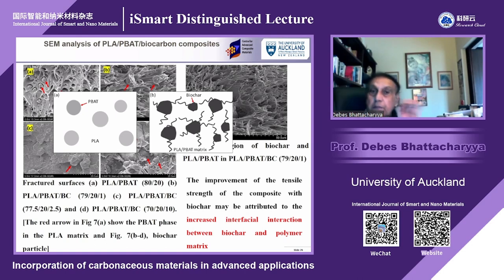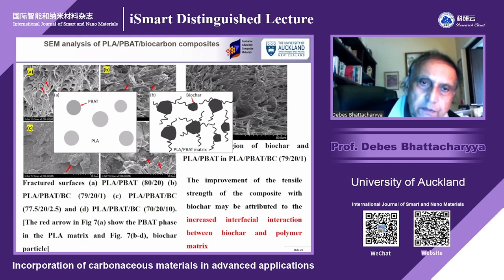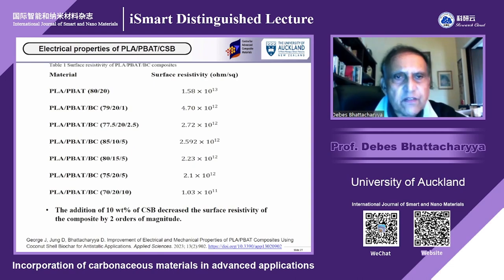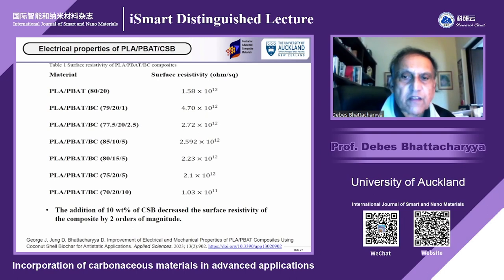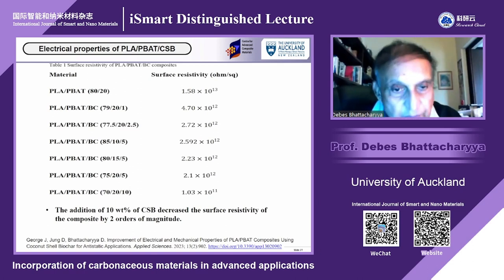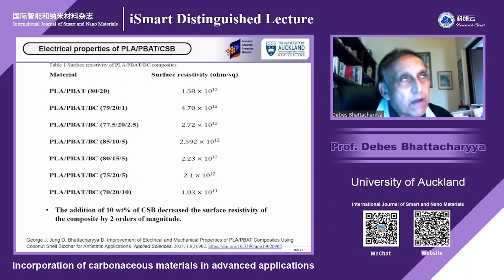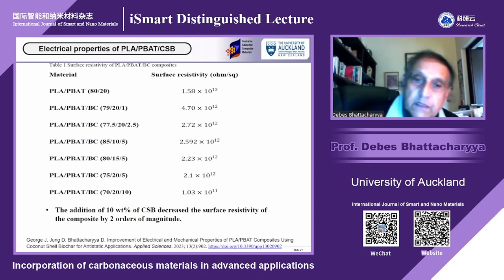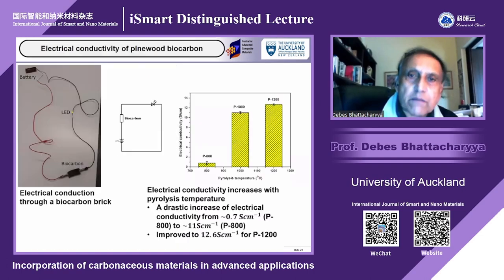Then you create some properties, but you have to use them very quickly. You cannot leave them for a very long time. So you see that this is a table. You see how the biocarbon we have changed from 0 to 10%. In Applied Sciences, we have published that the addition of 10% decreases the surface resistivity of composites by two orders of magnitude. The problem is, 10% is very good, but with that sort of material, you may find it difficult to 3D print. So depending on the eventual application, it is very good from the increased conductivity point of view, decreased resistivity, two orders of magnitude. So, like carbon black, it can be done.